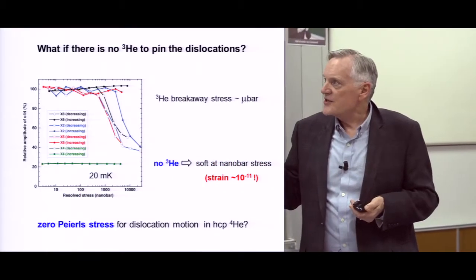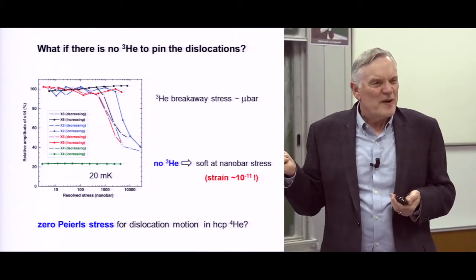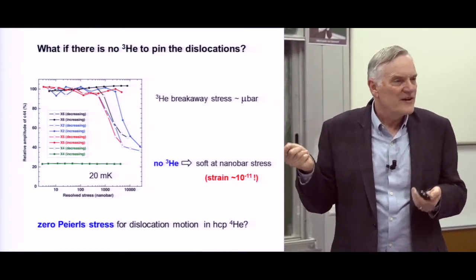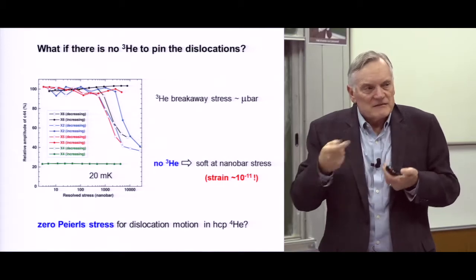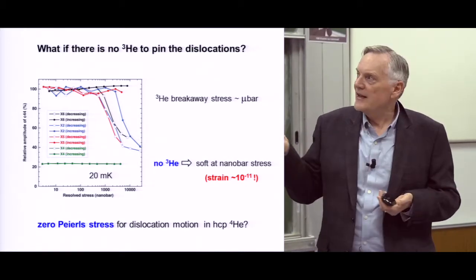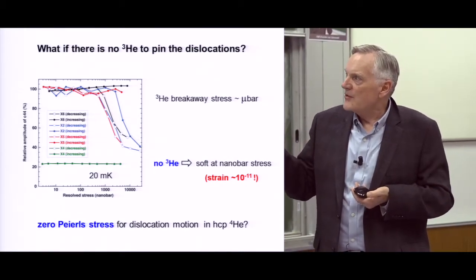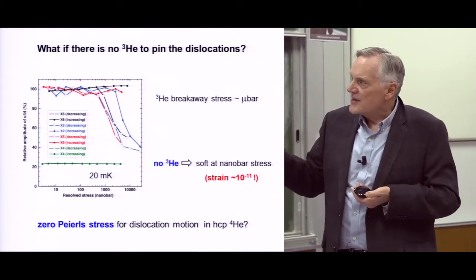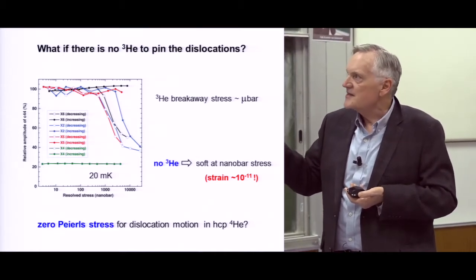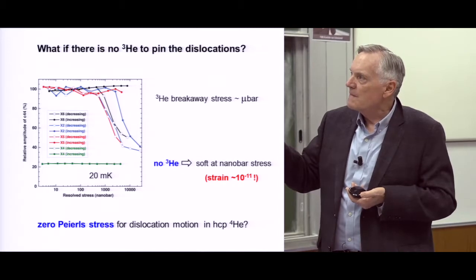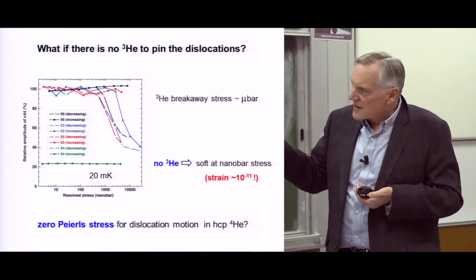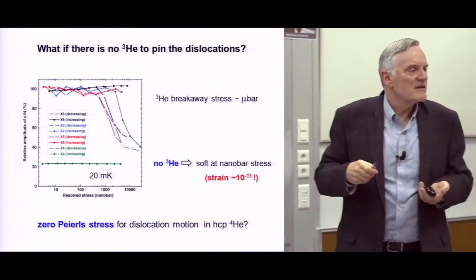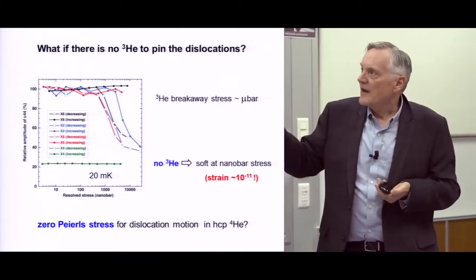And then there's the obvious question, what happens if you don't pin them? Well, you know, it'll be soft, but can it still move perfectly freely? These are some crystals that have a little bit of helium-3. This is increasing stress. This is shear modulus. This is increasing stress. And what happens with most of them, at some point, you've got enough stress that it breaks away. You rip the dislocations away from the helium-3, and they soften.